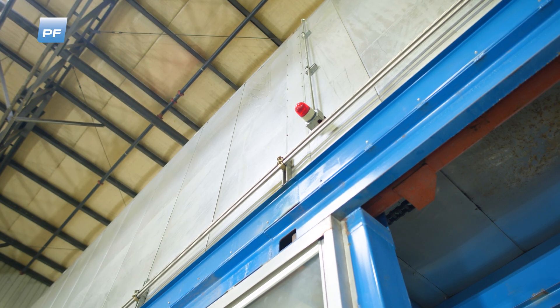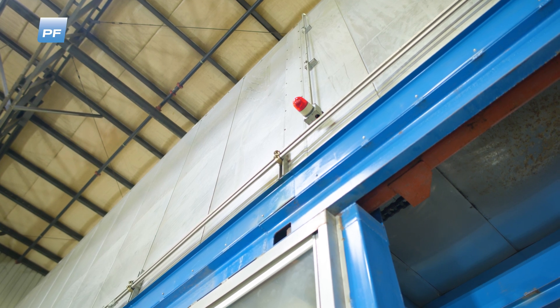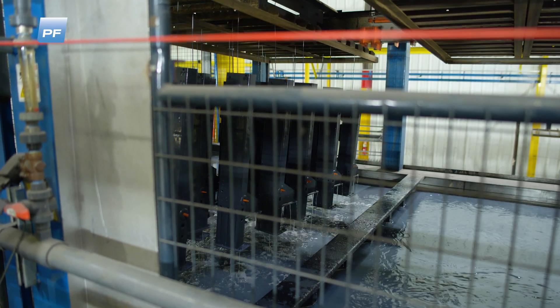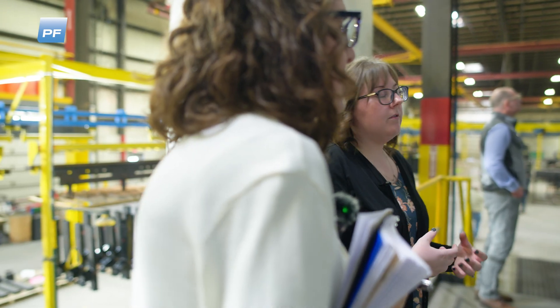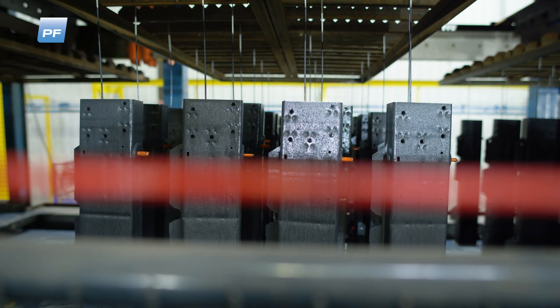As soon as that lowers, the light is on — that means electricity is now being applied to the parts and to the E-coat. On our very last tank is just an RO rinse because you can get what's called permeate drips on parts if that solvent is still on the part.